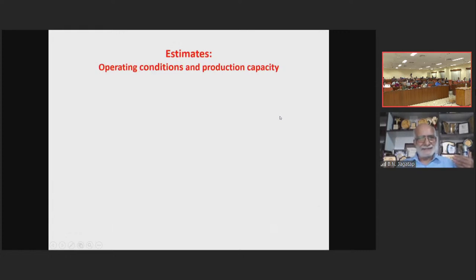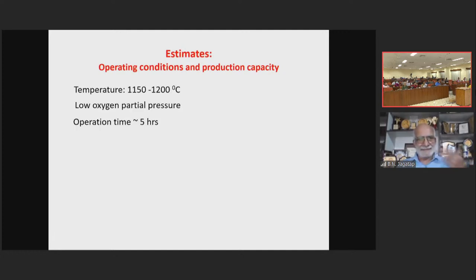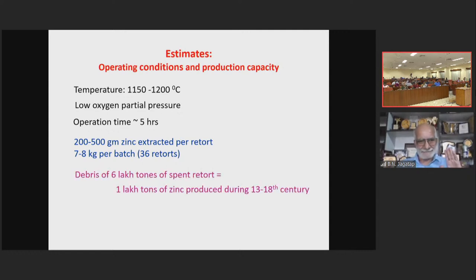Now, the scientists have also estimated the operating conditions and production capacity. The typical temperature here, in charcoal-fired operation, would be 1150 to 1200 degrees centigrade, with low oxygen partial pressure because it is all closed, and operation time is about 5 hours. Each retort would give you 200 to 500 grams of zinc. So 36 retorts in one batch operation will produce 7 to 8 kg of zinc. Now, around these mines, there is a debris of 6 lakh tons of spent retorts.